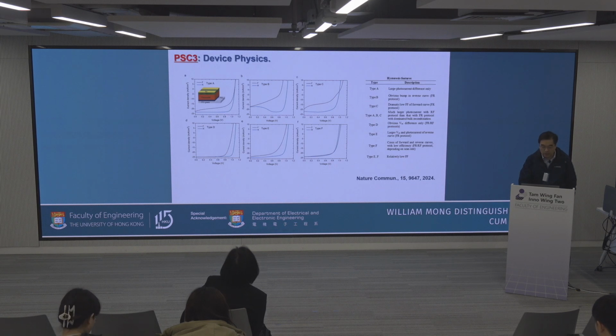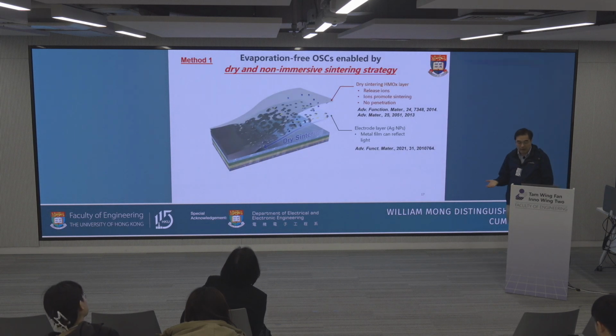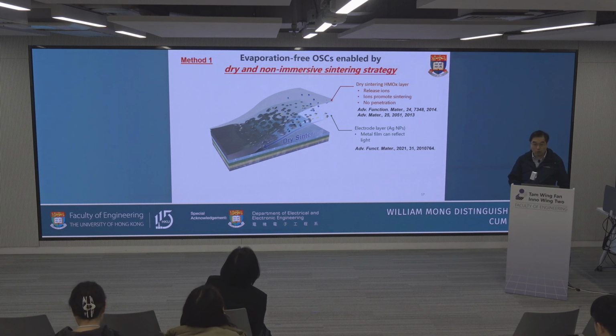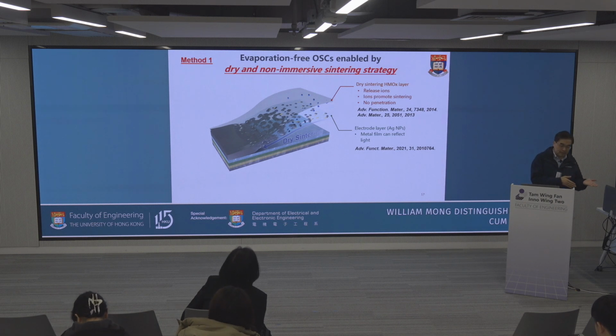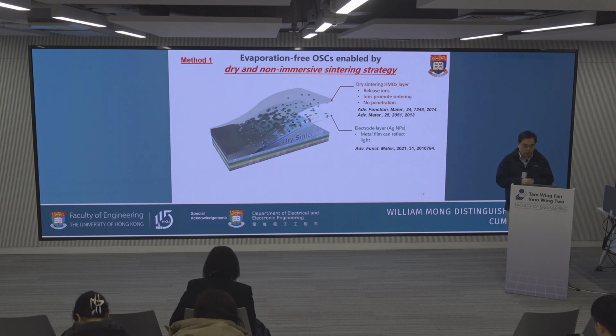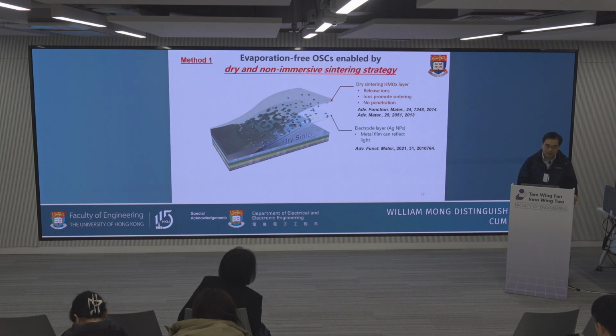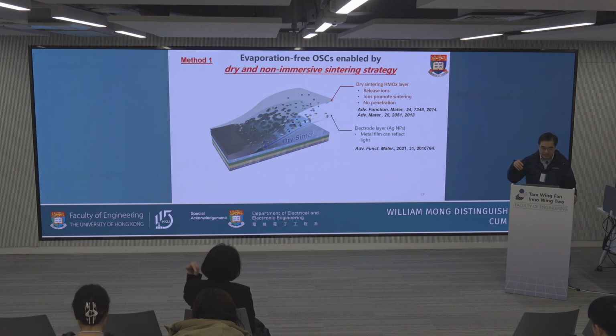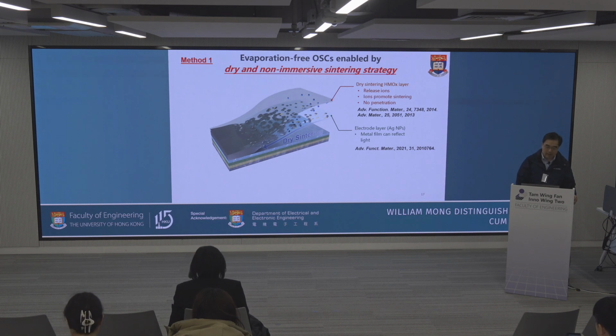How about the top electrode? People are still stuck with the high vacuum chamber for evaporation. Can we form the solution process electrode all the way from scratch, without glass, and use solution process at the last mile to finish the top electrode? We want to, but it is not easy, because the solvent we use for a top electrode will easily attack the organic and perovskite structure. That is the reason evaporation is safe, because it doesn't have that problem.